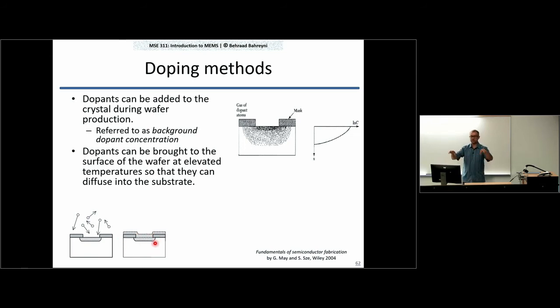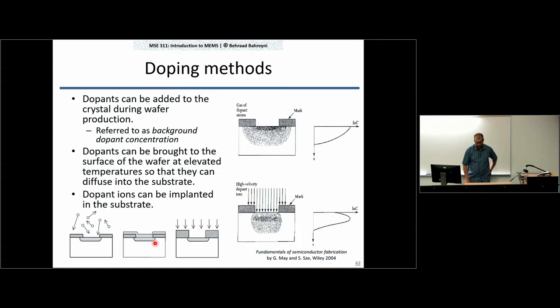So you deposit a film that has a lot of phosphorus in it, and then you let the phosphorus in the film diffuse into the silicon layer underneath. You can also do something different. You can take a phosphorus atom and just shoot it towards the substrate. And you shoot it at a high enough energy so that it penetrates the substrate, right? So this is called implantation. You're implanting these phosphorus atoms into the substrate.